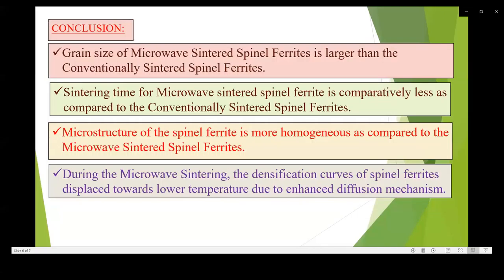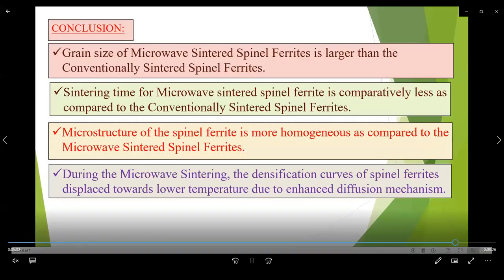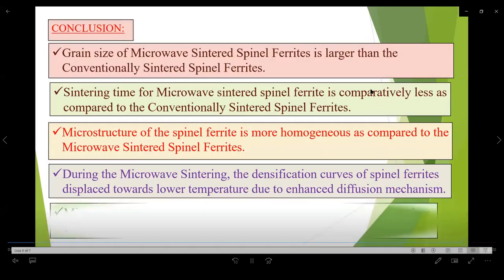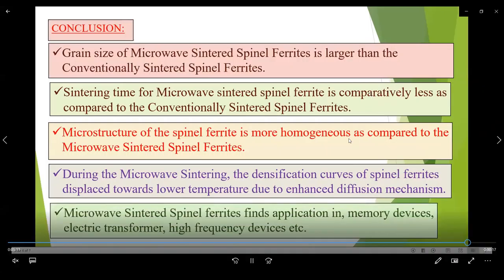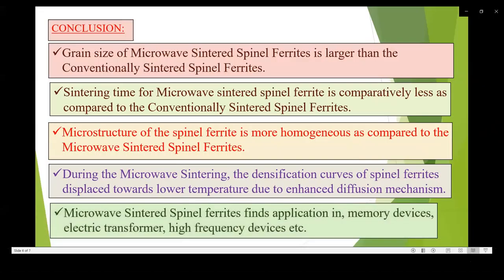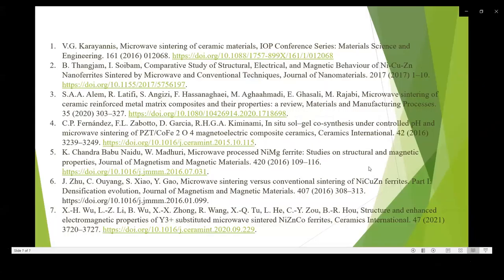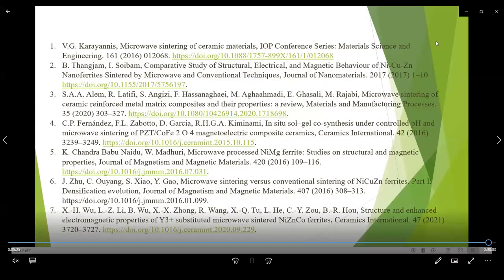During microwave sintering, the densification curve of spinel ferrites is displaced towards lower temperature due to enhanced diffusion mechanism. It has been observed that microwave sintered spinel ferrites find applications in memory devices, electric transformers, and high-frequency devices because of the above mentioned properties. And these are the references. Thank you.